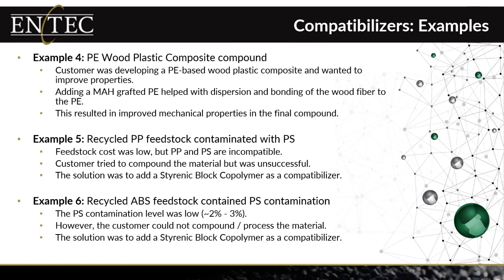Also, recycled polypropylene. We've had customers that have had the opportunity to get low-cost feedstock because it's contaminated with polystyrene. I had a customer that tried to make a compound out of that material. They weren't very successful because, needless to say, they're not compatible and the properties were not very good. But adding a styrenic block copolymer as a compatibilizer will then improve the properties.